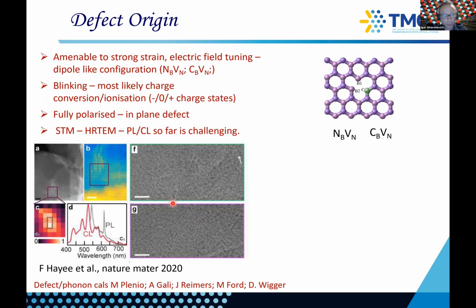And this really heroic work was done by Fariah Hayee in Jen Dionne's group at Stanford. And so you can do this correlation, and you can also map the strain fields, but you can never get a one-to-one single defect that is optically active to a single defect in a TEM.